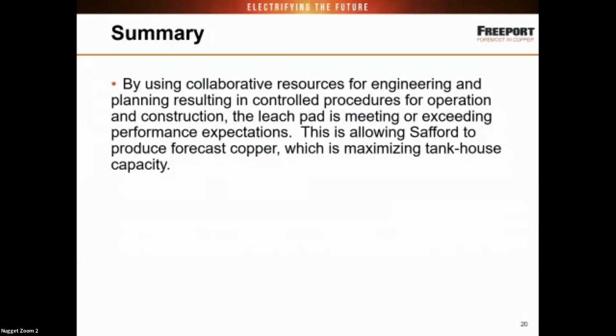So we ended up working with the leaching, coordinated with stacking, and we all collaborated. We actually put skid steers out on the pad. We had people around the clock watching and moving these big boulders and making things how they should be so that the stacker didn't have these problems. So we were able to successfully get through that initial lift and those issues with the slightly bigger raw material than we had planned for. Ground observers, 24-hour ground observers on the ground.